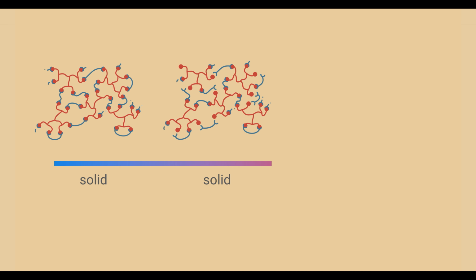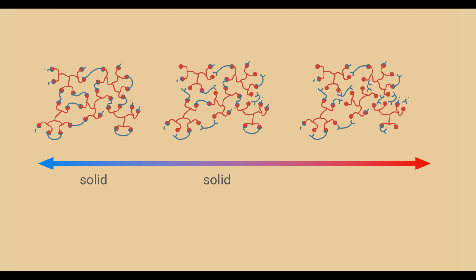At a certain temperature, so many Diels-Alder bonds are broken that the material no longer forms a single network and it transitions into a viscous liquid. This critical temperature, known as T-gel, enables reprocessing of the material. However, for healing to occur, it's essential to maintain the geometry, and it should therefore be done in a solid state below this T-gel. Upon cooling, the equilibrium restores, enabling the bonds to reform also over the interface between the two pieces, and effectively healing the damaged area.